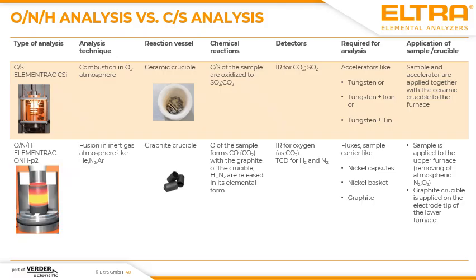In this slide, I just compared the two different techniques which are used for CS or ONH analysis, so that it's easier for you to evaluate the differences and which effects you should take care of when you have unknown powders. CS always means combustion in oxygen atmosphere, which just means you are releasing CO2 for the embedded carbon content and SO2 for the embedded sulfur content. The thing you can vary is typically the kind of accelerator, which just means tungsten, or tungsten and tin, or tungsten and iron. For an Elementrac ONH-p2, it's a little bit different.